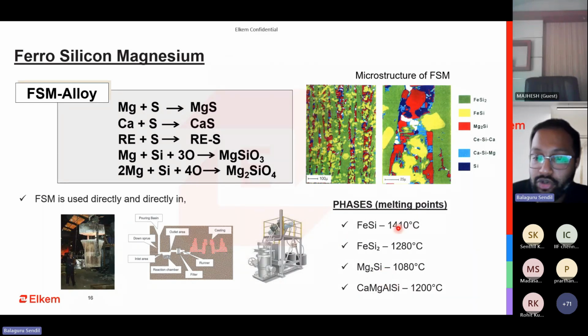If you look at the distribution of it, the majority will be iron and silicon, FeSi2. These are the phases that will be formed in all your ferrosilicon magnesium. And this Mg2Si and then calcium magnesium silicon. This again will be very little because the amount of magnesium in your ferrosilicon magnesium is not more than 7 or 8 or 9%. Again, how you get this microstructure is also very challenging. People who are making ferrosilicon magnesium will know that it is very challenging to get a uniform distribution of all these phases. So it's a lot of challenge to control this, because of this you see a very natural segregation.